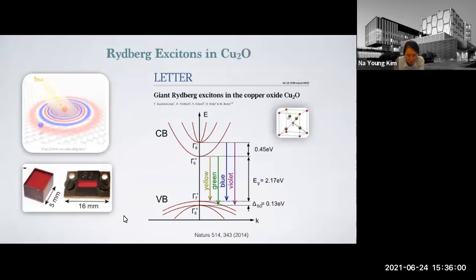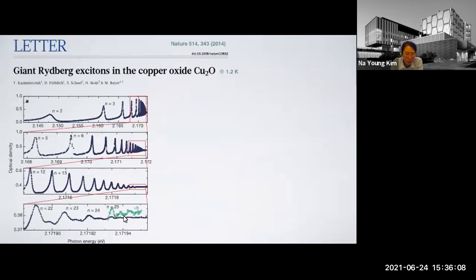And in the Nature paper, it's amazing what they show. Using a very narrow bandwidth tunable laser, about 1 megahertz, in fact a dye laser, this group managed to observe the n equals 25 Rydberg states at 1.2 Kelvin. This was the world record back then for observing the highest Rydberg state. And now n equals 28 below 1 Kelvin is the world record.